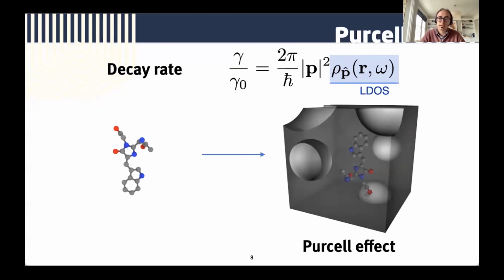So as it is a process that is an exchange of energy, you see here in this equation that I put here, the decay rate, so the amount of photons per second that we get from the material, depends on p squared, which is the dipole moment of the material, so the material property, but also depends on the density of states, this rho function, which is the density of states of the medium that embeds the source. And this means that if I take an emitter and place it in an environment with 0 density of states, it will not emit light. But if I put it in a place with very high density of states, the emission rate will be enhanced and the material will be brighter and brighter.